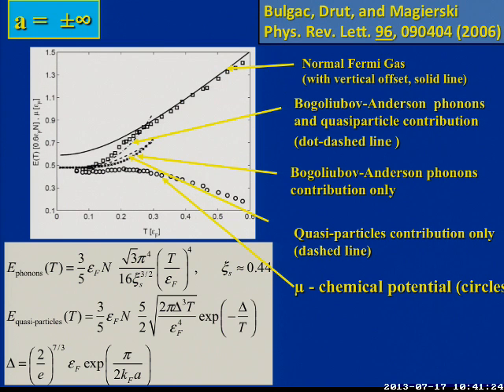Now, if you have a non-interacting Fermi gas, you remember the theory that if you write down the energy of the ground state, it's the energy of the non-interacting Fermi gas times a number, right? Now, you expect that number to be smaller than 1, so take it down by whatever number. But if you can calculate that energy as a function of temperature, you can take a non-interacting Fermi gas as a function of temperature. We took that and simply shifted it down. This is the black curve. So we took the non-interacting Fermi gas at a given temperature for given density, lowered it down in order to lie exactly on that. You see, above this temperature there is almost, at least visually, agreement between the two. At some temperature here, it starts deviating and it goes lower.